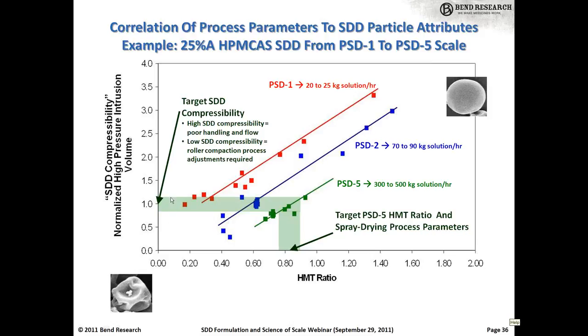So if the compressibility or the void volumes got too large, that also correlated with a low bulk density. And you got to a point where you just had flow problems and too much material. The material was too bulky to fit in the bins. So you had an upper limit that you wanted to stay below. And you also had a lower limit in terms of SDD compressibility, just because there was a pre-existing high-throughput roller compaction process, and it was not desirable to make any changes to this roller compaction process. So we had a fairly narrow, tight window that we wanted to stay within.